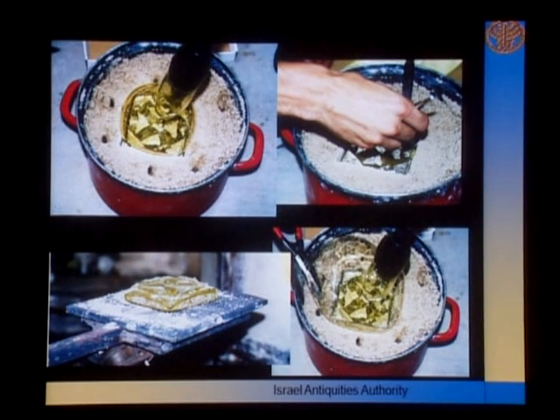Meanwhile, a thin blown blob was made on the blowpipe, and when the gold foil was fixed, the blown blob was attached to the tile, flattened and cut off the blowpipe. Then the margins were broken off. For the finishing, the tile was reheated in the furnace, and the edges were rounded by fire.